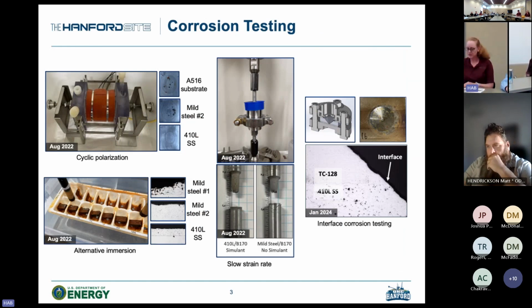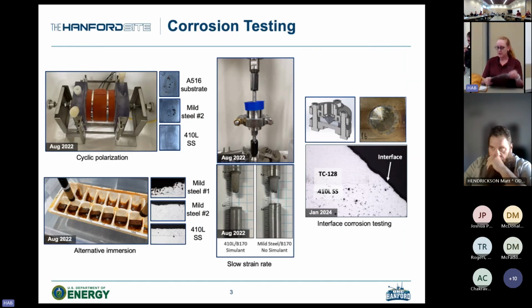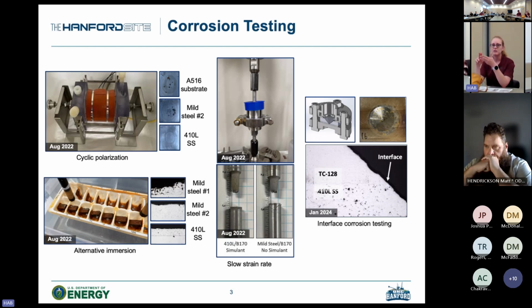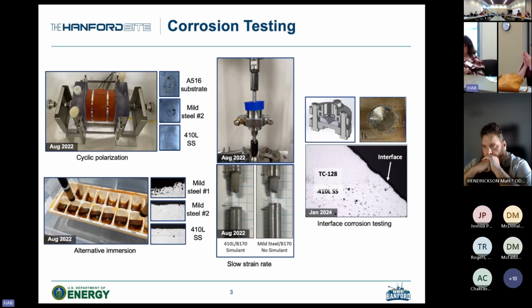Next slide, please. So in parallel to developing the equipment, we also performed corrosion testing to assess performance of the cold spray patch, be it within the annulus environment, or if it were to actually come into contact with tank waste. We wanted to know how that patch would effectively respond. So we performed accelerated corrosion testing, and the types of corrosion testing we investigated included cyclic polarization, galvanic corrosion, alternate immersion, slow strain rate testing, and then we also looked at hydrogen embrittlement testing. We started with 8 coating candidate materials that included mild steels and stainless steel, and we narrowed that down to the 410L stainless steel as being the ideal feedstock for Hanford site application.